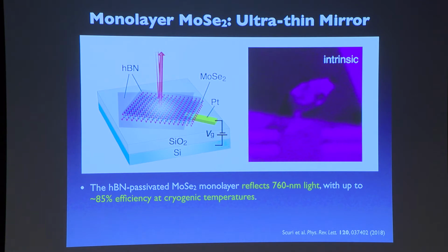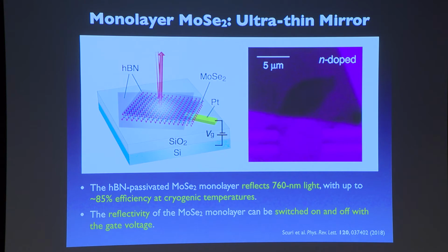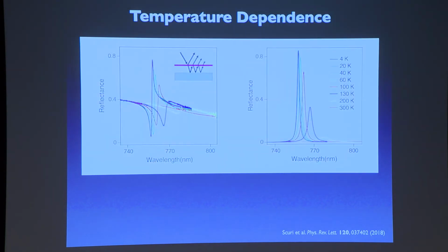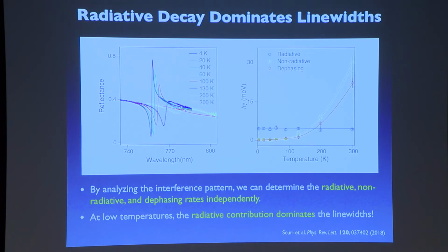They reflect back almost as well as gold metal. And because we can change their optical properties using so-called gating, meaning adding electrons or holes using the same mechanism that you use to make field effect transistors, you can turn the mirrors on and off by just applying a few volts. The reason we can do that is that what we have put down is a perfect semiconductor, meaning a semiconductor holding so-called excitons that are entirely lifetime broadened. And then we can quantify that by analyzing the reflectance spectrum that we measure. In this particular case, the line shape looks like a Fano line shape because we have two mirrors in the system: one resonant mirror, which is embedded within one continuous mirror.